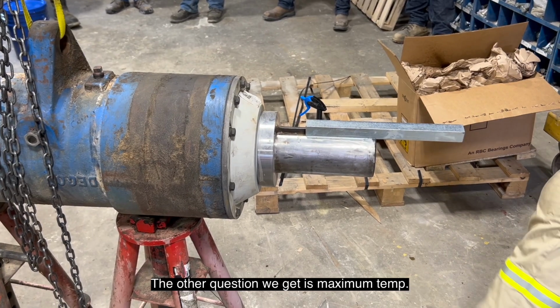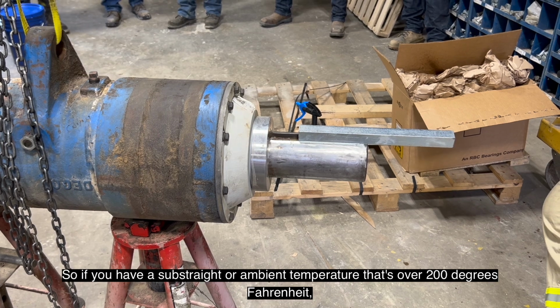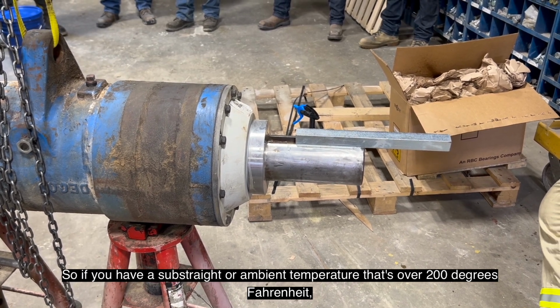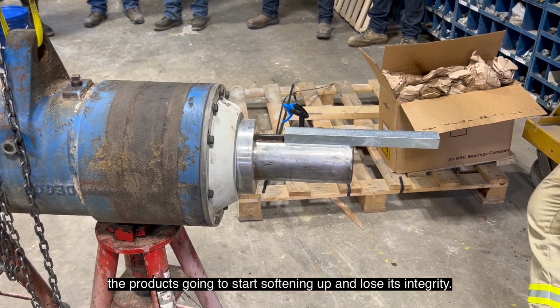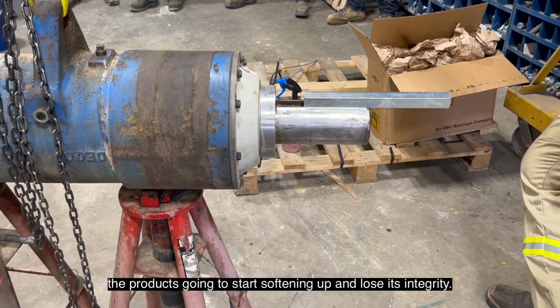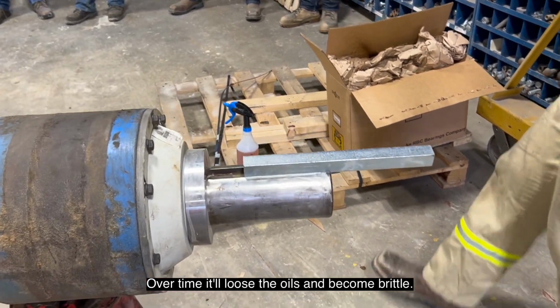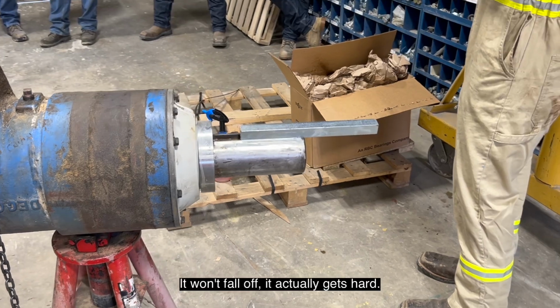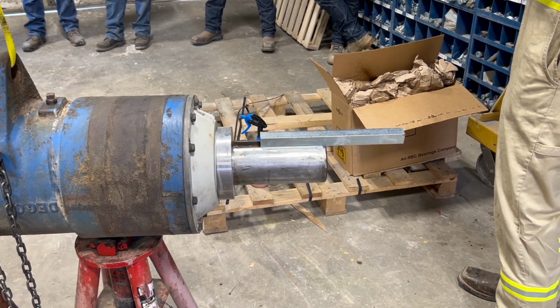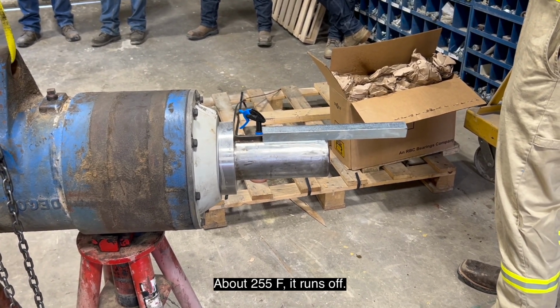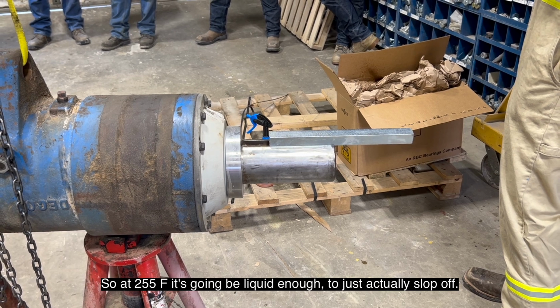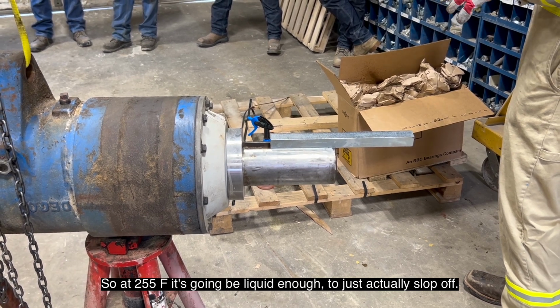The other question we get is maximum temp. If you have a substrate or ambient temperature over 200 degrees Fahrenheit, the product's going to start softening enough to lose its integrity. Over time, it'll lose the oils and become brittle. It won't fall off, it actually gets hard. At about 255, it runs off. 255 is liquid enough to actually slough off.